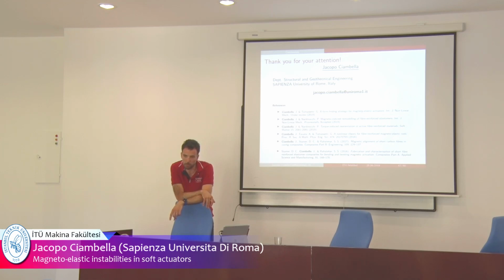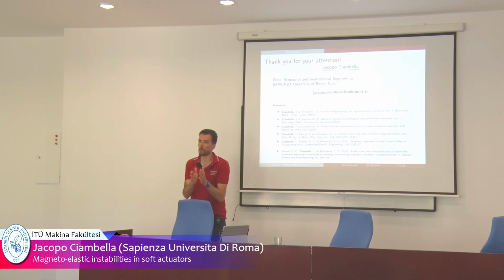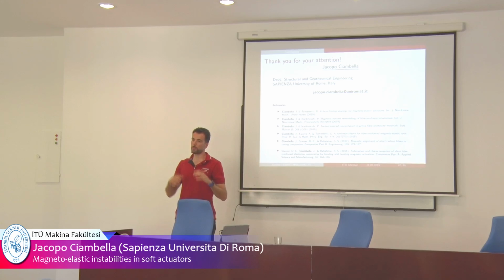for the mechanical properties. But consider the deformation of this specimen was very low, because the specimen was very thin. So it is true that the displacement is high, but the deformation is very low. So we were not concerned, for instance, that the interaction between the fiber and the matrix was not good, because we didn't expect to have deformation higher than 10% probably. But the problem with higher volume fractions of the fiber is manufacturing. You can either get fiber agglomeration if you go higher than 6% in volume, or you can have difficulties in mixing and sonicating the solution, so the fibers will stick all together. So we didn't manage to get above 6% for manufacturing issues.